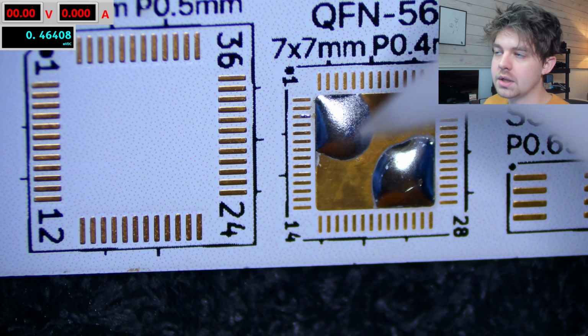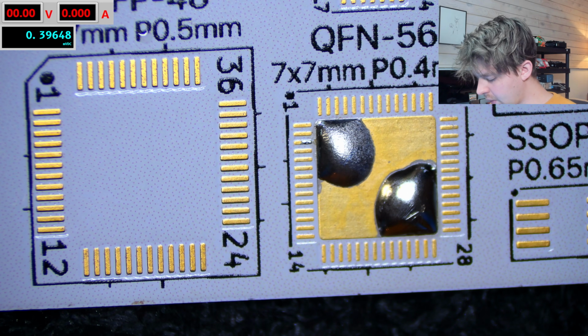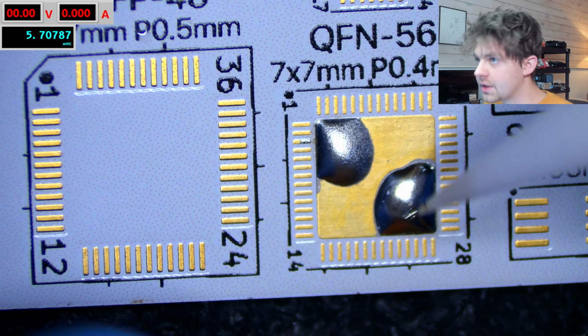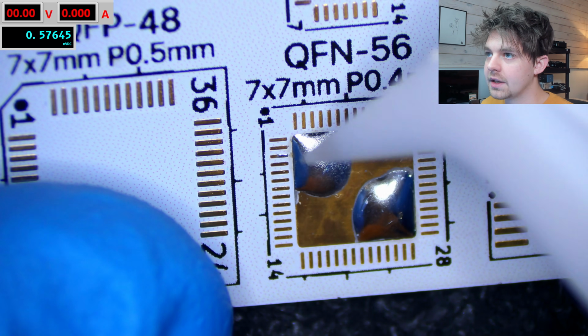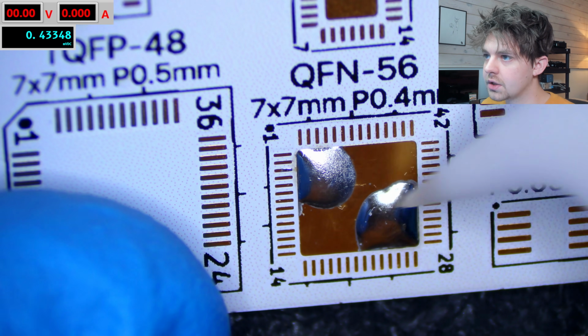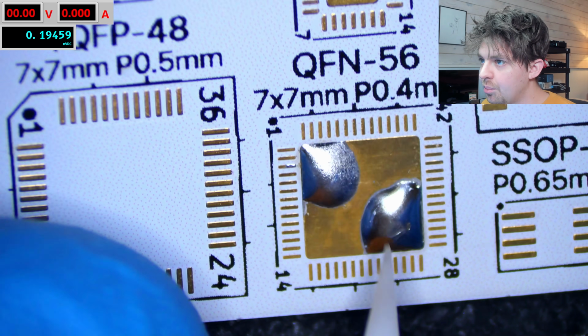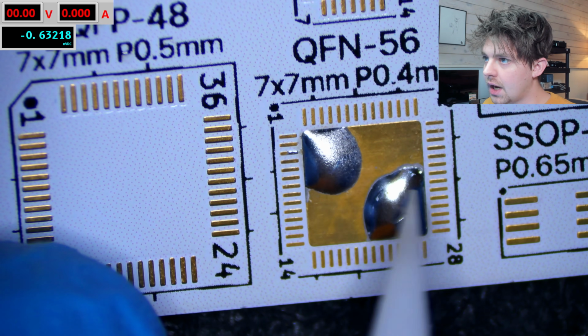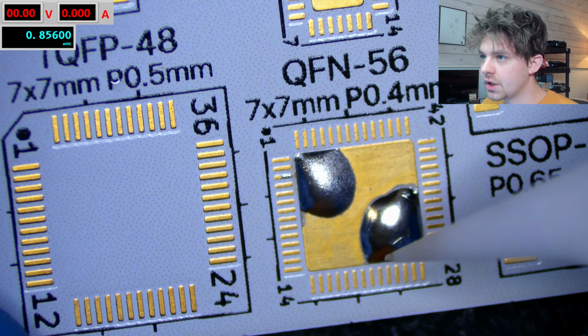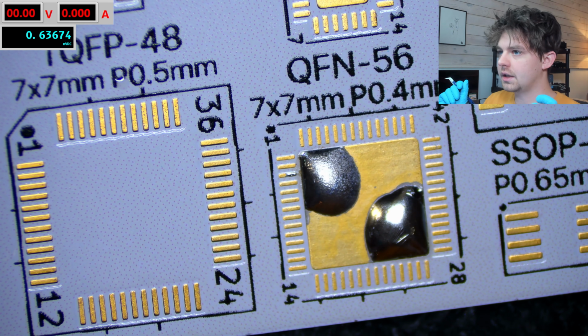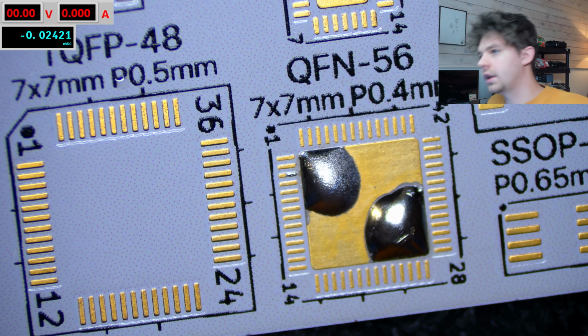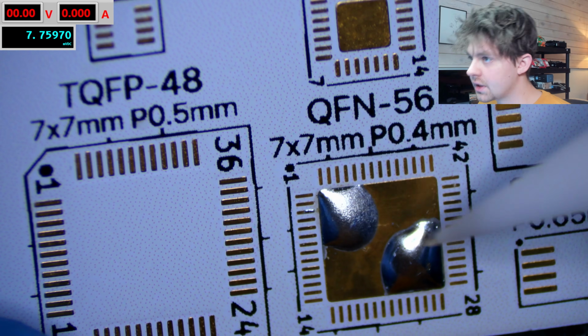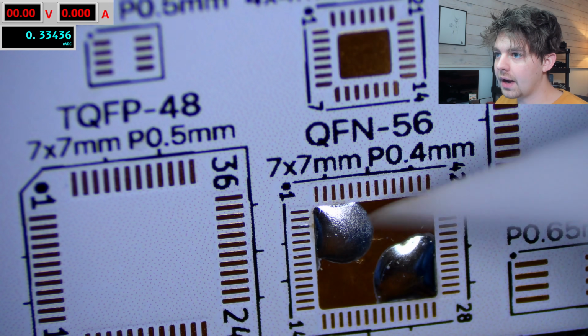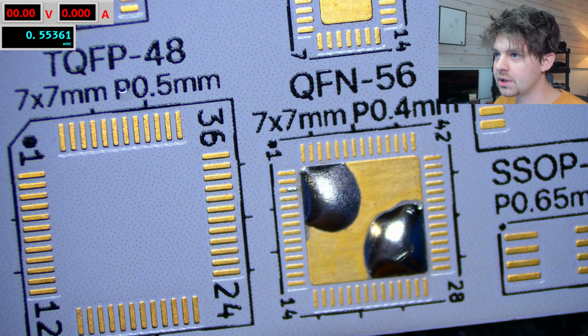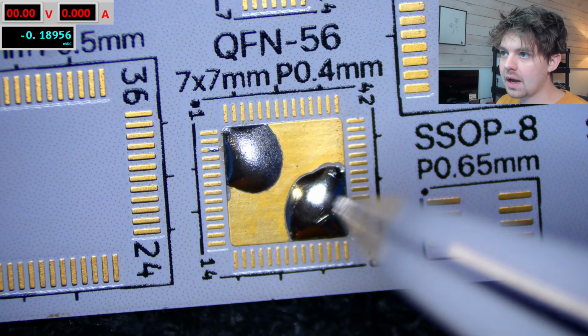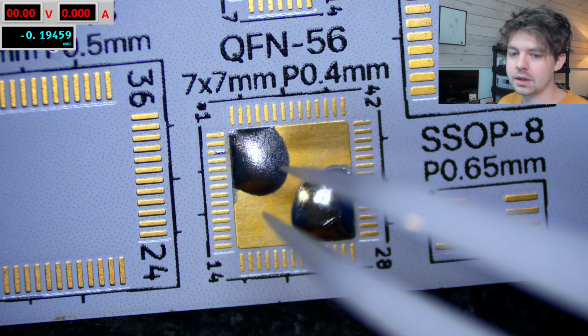And this is not what you want to see on solder joints. It's going to create weaker and a little more brittle solder joints than something that looks like this did initially, or like this eutectic solder looks like now. So you can see the eutectic solder is still fully shiny. Generally speaking, this is just instantly solidifying and is not able to really move around while it's solidifying, if that makes sense, which creates this nice shiny joint. And keep in mind, this was without any component or any tweezers that could potentially move the component around. So I'm going to show you now what happens if you move this stuff around while it is solidifying.